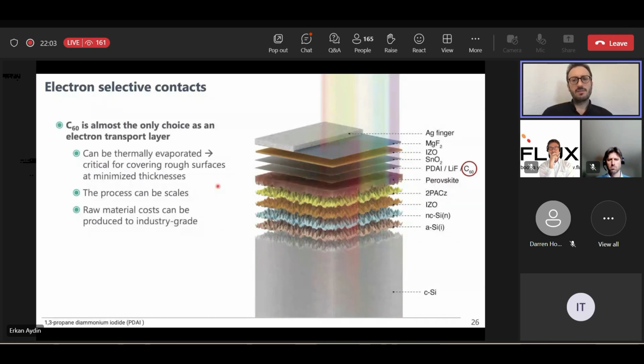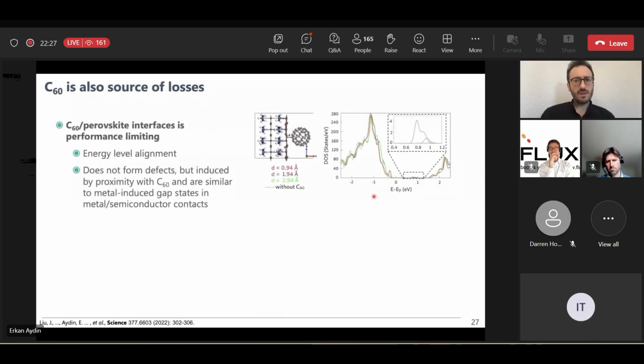The very first thing that we did some time ago, it was in 2022, again with my colleague Jian Liu, and actually we looked at the perovskite C60 interface, because the overall idea was really minimizing the voltage losses as much as possible. So one thing that we did, we tried to figure out why there is a voltage loss even if you bring the energy level alignment of the perovskite and fullerene as close as possible.